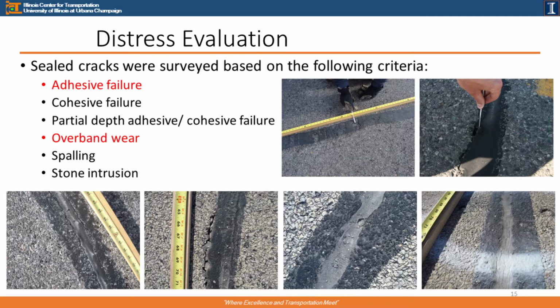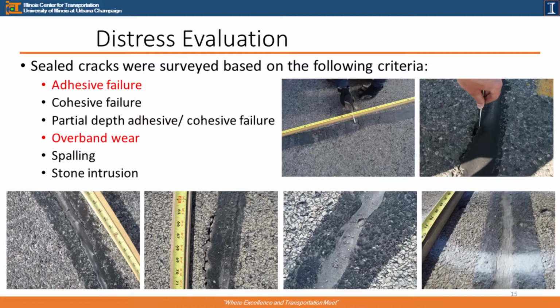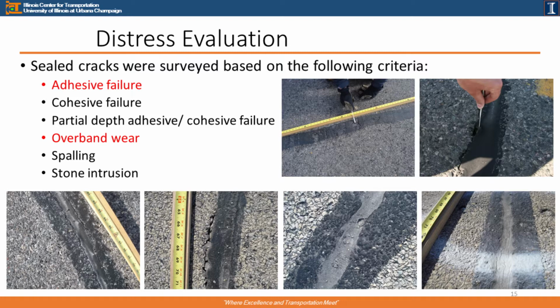So how did they evaluate distress? I think most of you are familiar with the distress related to crack sealing. Let's go over them one by one. The most common distress with crack sealant would be adhesive failure. Did you see the adhesion failure here, the line? I hope you can see, right? And then second will be cohesive failure, okay, within the sealant. And the third one will be partial depth adhesive or cohesive failure. So when you go out in the field, you need a knife or something sharp so you can see whether it's full or partial depth. The second most important failure or distress is so-called overband wear. Okay, most contractors are using overbanding. So we need to make sure there is no failure.